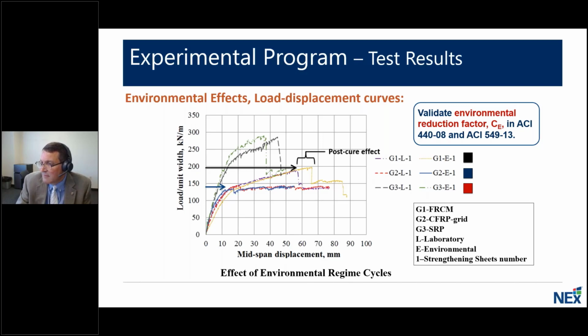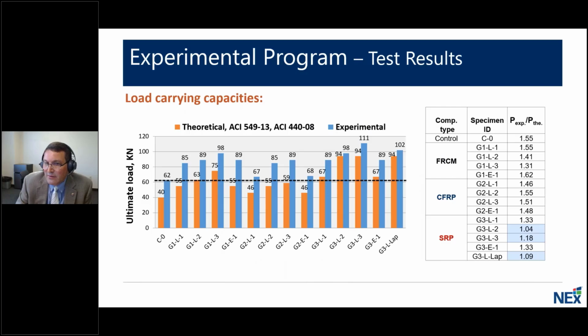And again, there you can see the difference in the red system, which is the G3 system using the SRP system. And again, no significant degradation for the one-ply conditioned. As illustrated in this slide, we can see that ACI 549 and also 440-08 standards are all conservative, which is good. The safety factor was generally 1.6 to 1.3 for one-ply to 3-ply for the FRCM. The steel reinforced polymer system had the lowest safety factor in this study, which you can see highlighted in blue. So that's also an interesting finding, that it's not as conservative.